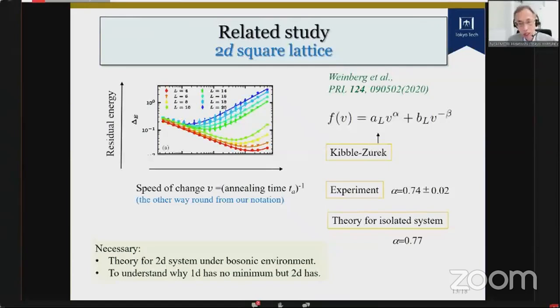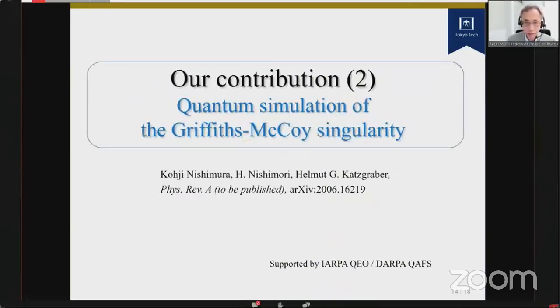So it's a pass. In the one-dimensional case, we found that the D-Wave qubits are under a bosonic environment. But in two dimensions, the experiment agrees with the theoretical prediction for the isolated system. So probably, I myself think that a theory for the two-dimensional system under a bosonic environment, if it is developed, would lead to a very similar value to this prediction for the isolated system, but we don't know. This again prompts the development of a new theory. And also, in the one-dimensional case, we didn't observe such a minimum for each curve. So this part should also be resolved in the future.